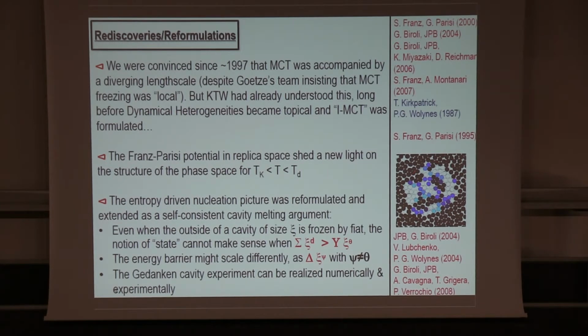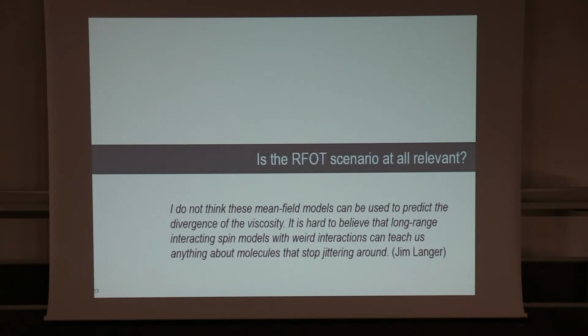And also this idea of a cavity is a kind of Gedanken experiment that can be realized numerically and maybe experimentally as well. Something else that we discussed in our paper with Giulio is that maybe the energy barriers scale with a different exponent psi as compared to the surface energy, calling it psi after the droplet theory papers of Daniel Fisher and David Huse. So that was around 2004, and then with people here, we got the first numerical experiment showing that something like this seems to happen in model glasses.